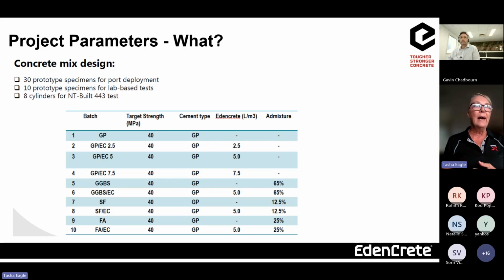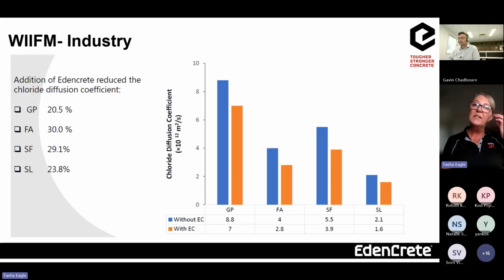We've obviously had some specimens in the lab, and the key thing we've done with the specimens in the lab, and I'll show you these results coming up with these 10 different mix designs, is that we've conducted NT-Built 443 testing, so chloride ingress testing. So what Kod and the team at Curtin University have, and this is a snapshot for everyone, have been able to establish when they did these samples in the lab and tested them for the chloride diffusion coefficient, is you can see here with the different mix designs where we've played with 100% GP cement, a mix design where it's a combination of GP and fly ash, same with GP and silica fume, and then obviously the last one there being with slag.